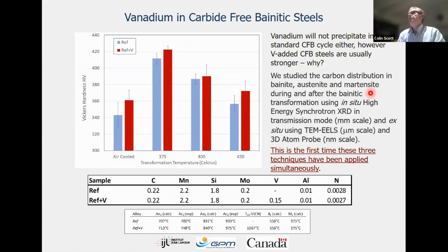Now, carbide-free bainite steels, obviously you need more carbon. And usually you're looking at least 0.2 weight percent, sometimes more. We know that vanadium won't precipitate in a normal CFB cycle. That's quite clear from the thermodynamics. But when we do the actual measurements, we do see that adding vanadium does make these steels a little stronger.